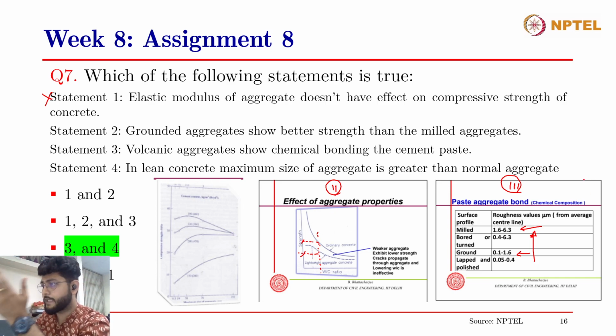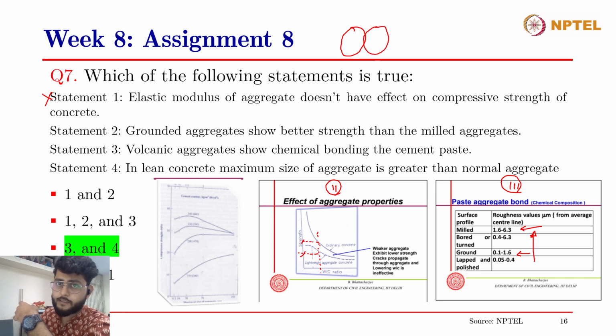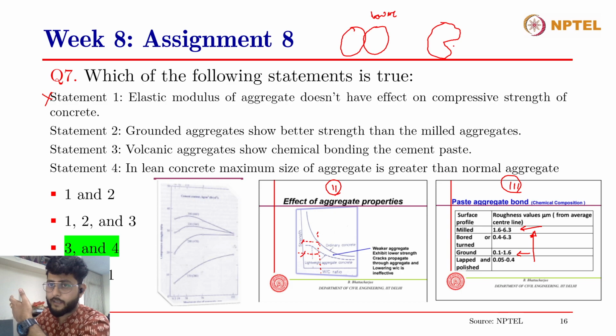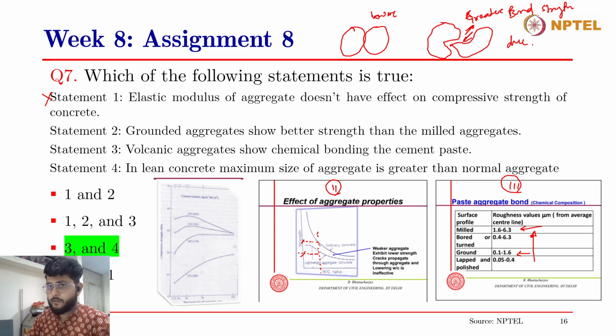when the surface of a given aggregate is rough, it provides a greater interlocking bond between the aggregates. So let us say this is a round aggregate and this is another round aggregate. The shear bond between these aggregates is lower as compared to irregularly shaped aggregates coming from a milled kind of aggregate, which has somewhat of an irregular shape. Now when these two are sheared off, the bond strength is higher due to the interlocking, right? So this is milled aggregates and this is ground aggregates.